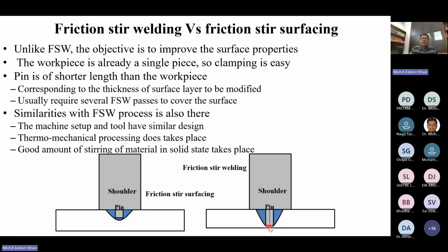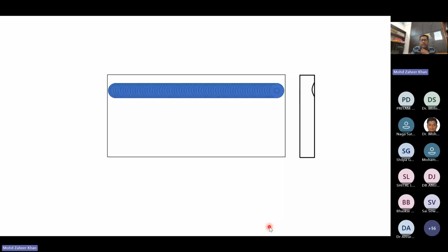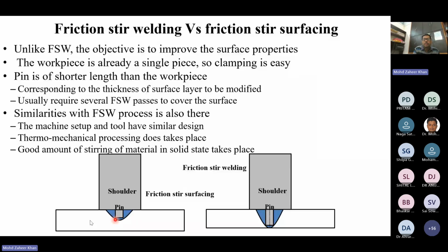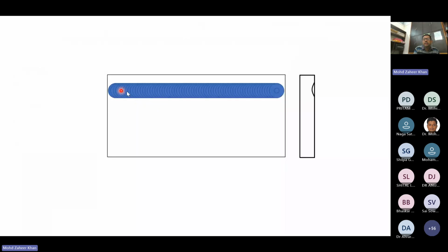Just like friction stir welding, thermomechanical processing also takes place. A good amount of stirring of the material in the solid state takes place, and therefore there is a sufficient amount of grain refinement and the properties of the material improve. But remember, this surfacing has to be done on the entire top surface of the plate. So the entire plate has to be surfaced. If we are just doing one friction stir processing pass, then only this portion of the material will get the surfacing operation.